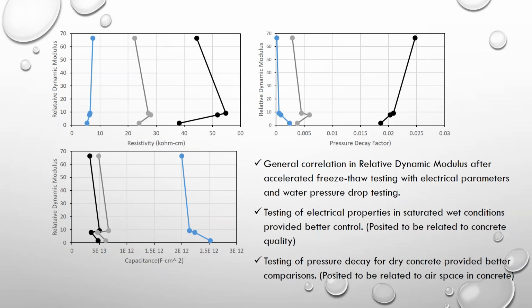And we see that the better performing concretes with a higher relative dynamic modulus are those samples with a higher resistivity and those with a lower capacitance. So this represents those concretes that have a higher cement factor, and so the higher quality concrete. So they'll give you better behavior, and the wet condition helps us to give us better control of the test samples.